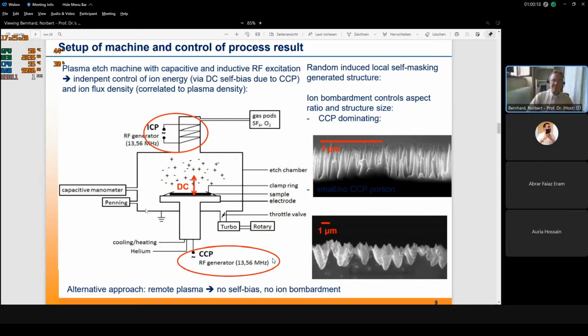In principle, it's a high vacuum chamber where we have here a capacitive coupling from a high frequency generator. We use 13.56 megahertz. And here we have an inductive coupling through a coil of the same frequency. Here we have the gas inlets, I mean, sulfur hexafluoride and oxygen. These are standard gases, but there can also be other gases used. The essential gas, or the essential constituent or atom which we need, is fluorine, because fluorine is the one which really etches the silicon.